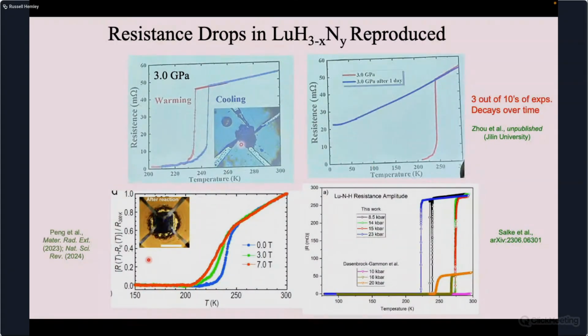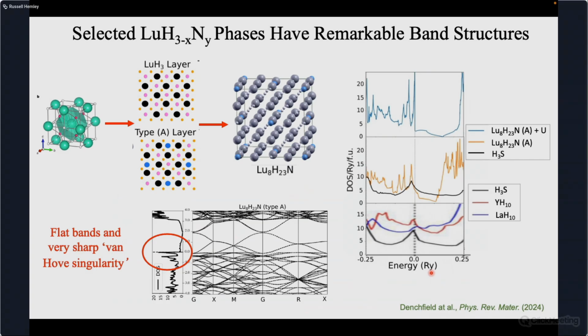There's another study, a very similar study that showed a magnetoresistance shift that's very similar to what you would expect in superconductivity. And here again, I show the results from our experiments. So this is work that's ongoing. It's very challenging. It's really a problem in chemistry and synthesis rather than a challenge for the transport measurements. But it's in a very accessible range because we're working at quite low pressures. How can we understand this theoretically?